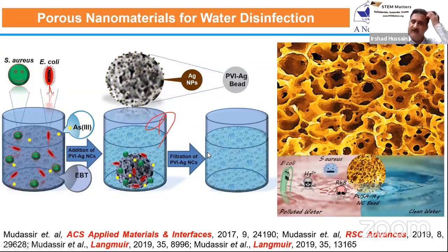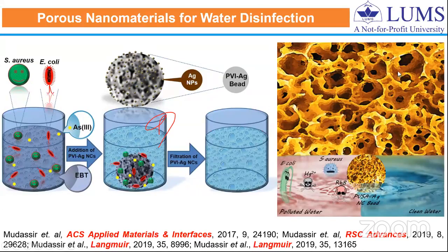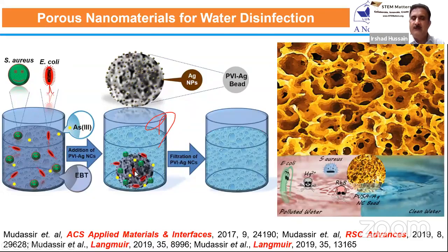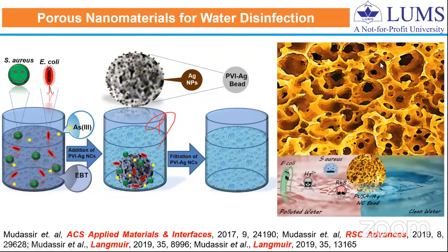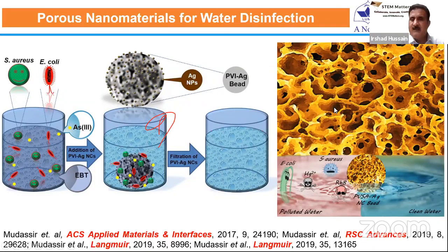Apart from these type of applications, we have also recently designed these microporous polymers. This is basically polymer beads in which you can control the chemistry of these polymers. You can control the pore size, and then you can infiltrate different nanoparticles, including silver nanoparticles. And we have used these kind of porous polymers not only to remove organic and inorganic pollutants from water, but also to kill bacteria in water streams. So this was all about my work related to biomedical applications of these materials.